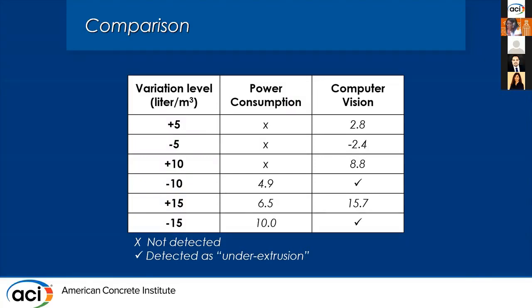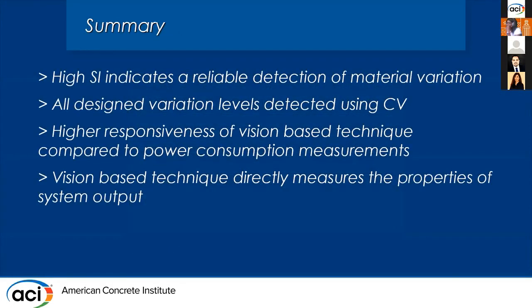And for the power consumption technique, as you can see, for 3 of the variation levels, plus minus 5 and plus 10 liter per cubic meter, it was not able to detect the variation in the printing material, but for the higher levels, it could easily detect it with very high sensitivity indexes. So in general, I could say that the technique based on computer vision had a better performance, a high accuracy, and a very high sensitivity and responsiveness to variations in the material viscosity. And one reason that comes to my mind is that that technique is based on direct measurement of the properties of the system output rather than relying on a correlation between the viscosity of the material, for example, and printability or other properties.